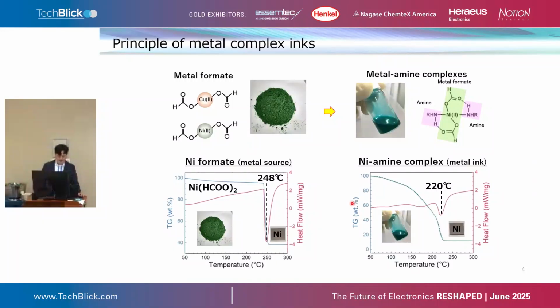And then, I want to discuss what the reaction principle of the complex inks is. The principle is actually the use of metal formate as a raw material of the ink. And the important property of the metal formate is that it can be reduced at high temperatures, and we can obtain pure metallic films. But the metal formate is actually in a powder state. So if we want to print it, we need to dissolve it into amine solutions. And in the case of the nickel amine complex, it can also be reduced at high temperatures, and we can obtain the metallic film after the reduction process.